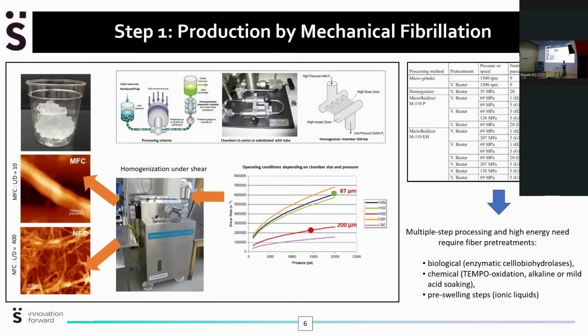We do it in the lab with an homogenizer. It's actually a high pressure chamber where pulp suspension is circulated many times under high pressure in order to introduce the fibrillation of the cellulose. This can be done in different interaction chambers in order to introduce high shear rates on the material. And depending on the number of steps, you get here either, for example, microfibrillated cellulose or nanofibrillated cellulose.